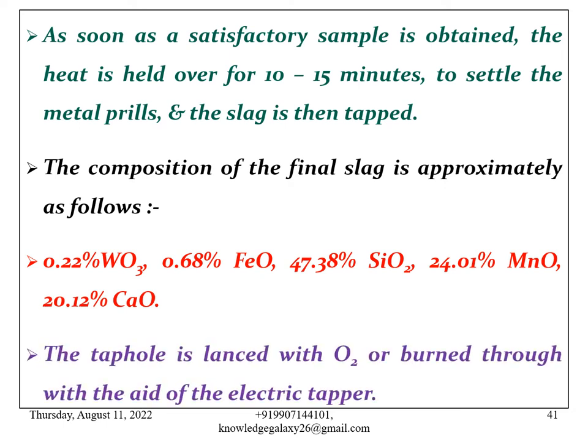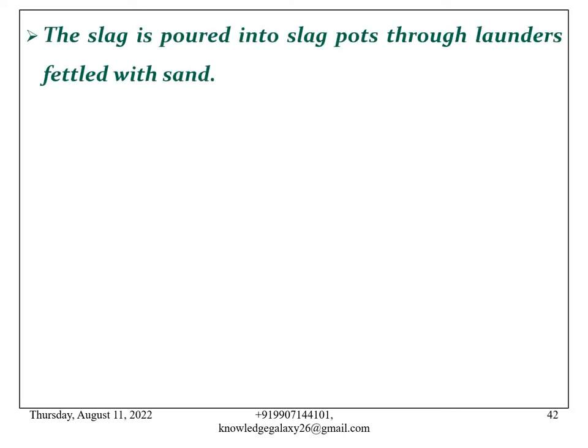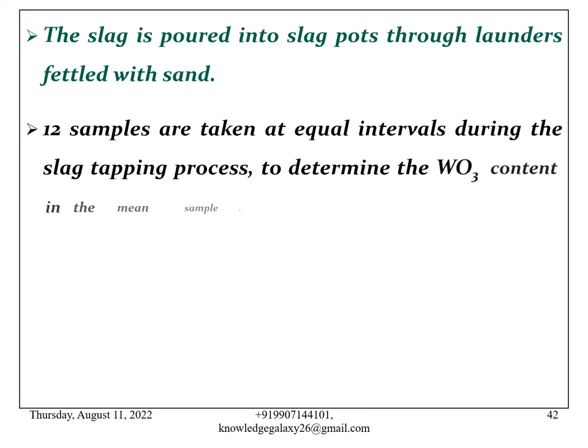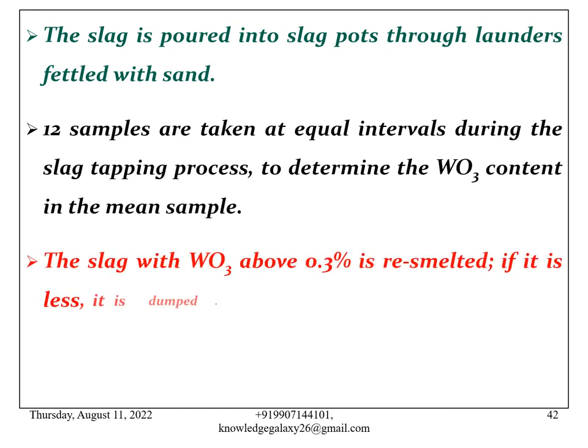The tap hole is lanced with oxygen or burned through with the aid of the electric tapper. The slag is poured into slag pots through launders fettled with sand. 12 samples are taken at equal intervals during the slag tapping process to determine the WO3 content in the mean sample.